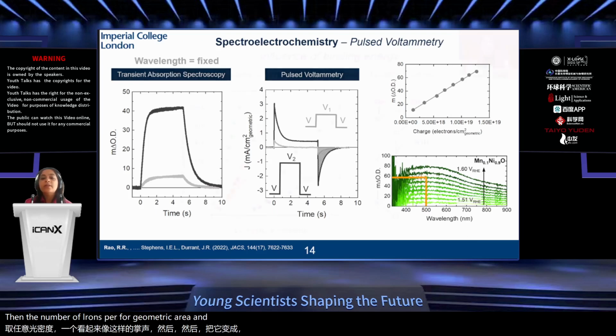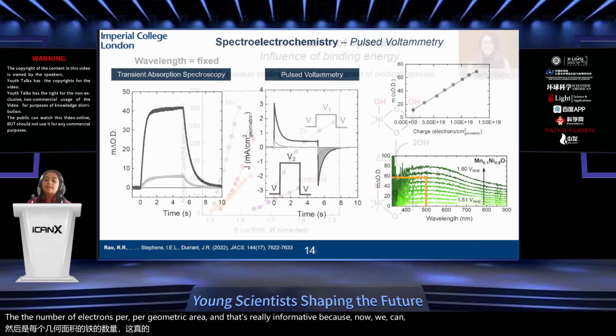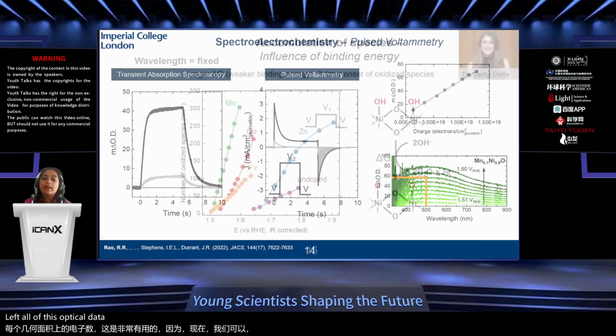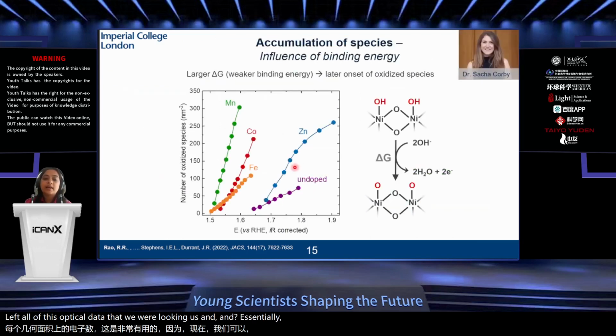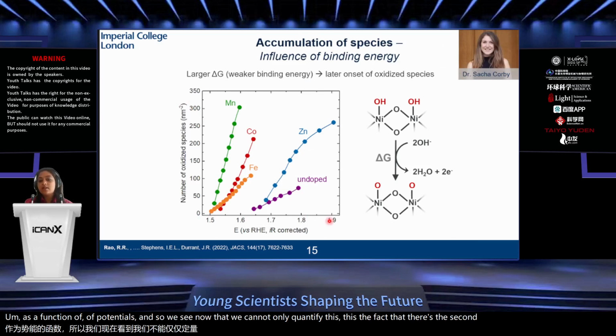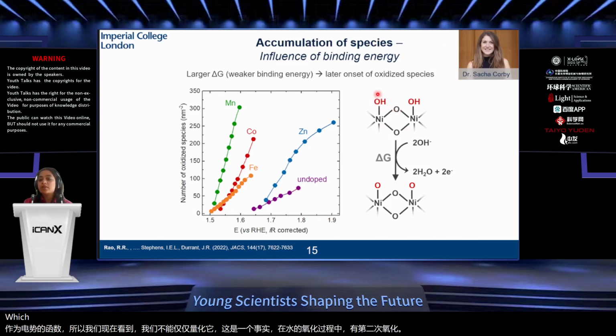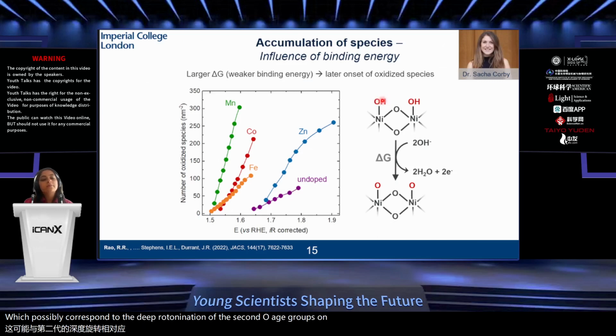And that's really informative because now we can collect all of this optical data that we were looking at and essentially plot it as a quantified number of oxidized species as a function of potential. And so we see now that we can not only quantify the fact that there's this second oxidation within the water oxidation regime, which possibly corresponds to the deprotonation of the second OH groups on the surface, but we can also start quantifying the number of these oxidized species that are forming.